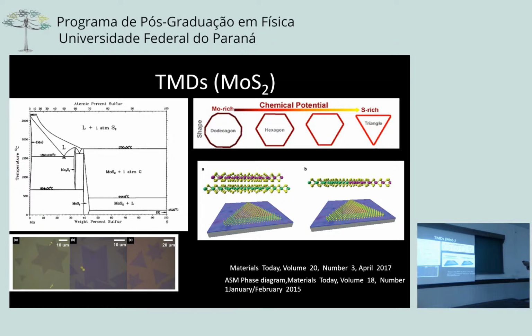What it means, like a line compound, gallium arsenide, indium arsenide, or all of these line compounds, they have a single point of composition, 50-50. If it's off from the composition, it's going to have completely different properties. MoS2 has a big solubility range. It means if it's off composition, still it's the same crystal structure. That opens up a lot of possibility.